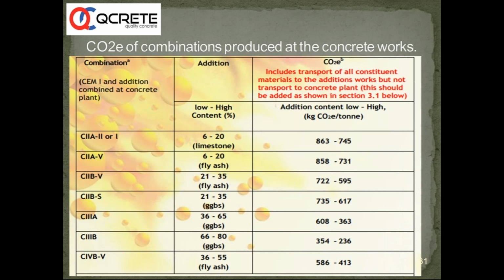For example, at the last you can see when you are adding about 36 to 55% of fly ash, you have a carbon dioxide production per cubic meter of concrete of about 586 to 413 kg, which is comparable with the 36 to 65% of GGBS. So we are not really comparing the two products, but here fly ash and GGBS are almost on the same scale, with a small difference, when we are talking about reductions in the range of 36 to 65%. So this is a significant contribution by SCMs, especially you can see fly ash.